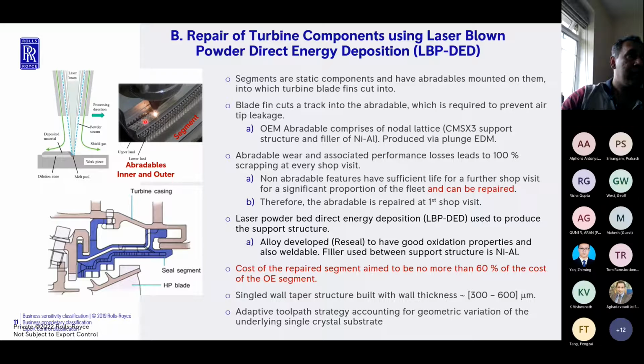It's been built here, and as this nozzle keeps moving and translating, you'll end up building the abradable structure on that surface. So the most important thing here is that, okay, you've built up, you've repaired the existing abradable with a new abradable. Can you now qualify the mechanical integrity of this abradable such that you do not have any form of deficit in properties compared to the OE condition?